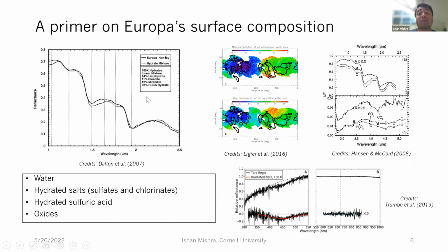The reason there are a lot of sulfates is because Io is spewing out a lot of sulfur, and that gets trapped in Jupiter's magnetosphere and finds its way to Europa's surface, primarily on the trailing hemisphere as Europa is orbiting. So its back, trailing hemisphere gets most of the bombardment. And so there's a lot of sulfur, and so sulfur products. Those decide the bulk spectrum, the bulk continuum of the spectrum.